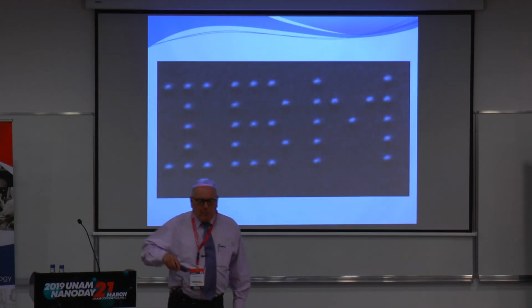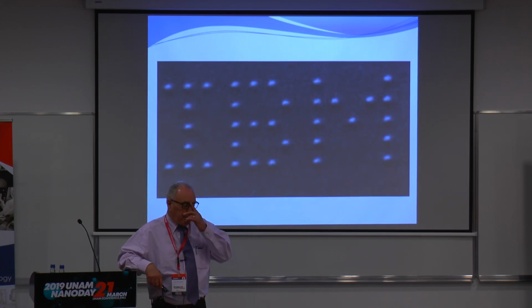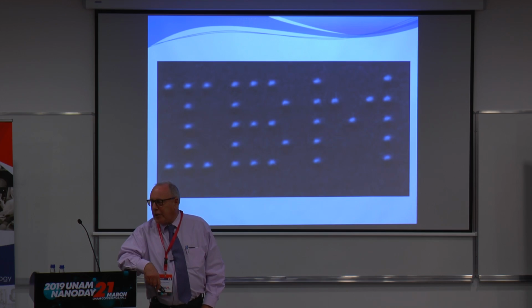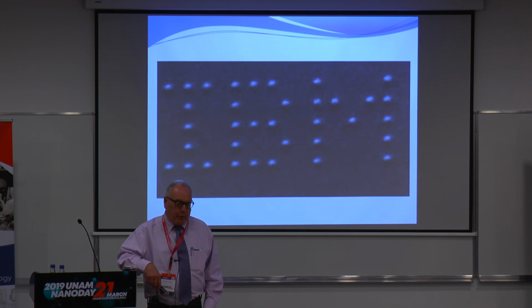And then in those 6 panels, beginning with the top panel here, this is when the xenon atoms are first sputtered onto the surface. And the point is, at this point, there's no structure, there's no order to them. And then an order gradually comes along here. And then they have made the letter I here. And then they have added the letter B. And they finish up with this image here. In other words, they've spelled IBM with 35 xenon atoms, just in case anybody had any doubt of who they worked for.